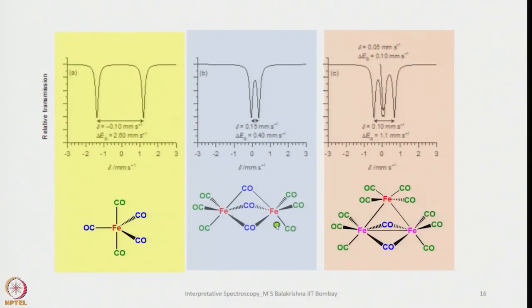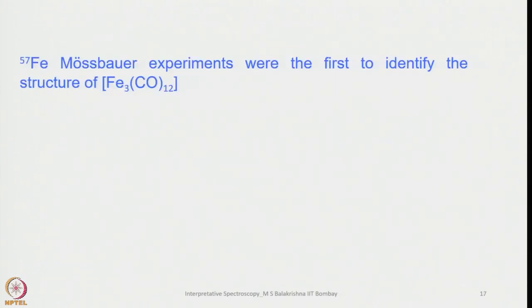You can see both of them appear to be in a typical regular octahedral geometry, whereas here we have one iron in a typical octahedral geometry, and these two have two bridging carbonyls. These two are of one type, and this is the other one. Obviously, you will expect this in a 2:1 ratio. That's what is observed here.